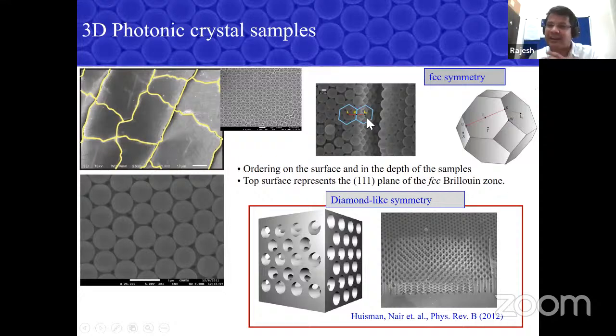And this is a crystal, as I said, so it has some symmetry. These crystals have a face-centered cubic symmetry, and the Brillouin zone is shown here. And this is a zoomed image of the sample. If you look closely, you can see the top layer, and below that, the second layer is also grown very nicely. And this is one type of symmetry of a photonic crystal people use. There is an altogether different type of symmetry, a diamond-like symmetry, which makes these samples extremely difficult and which is not possible with us. Only, I think, 4 groups in the world are able to make these kinds of samples, using silicon wafers.